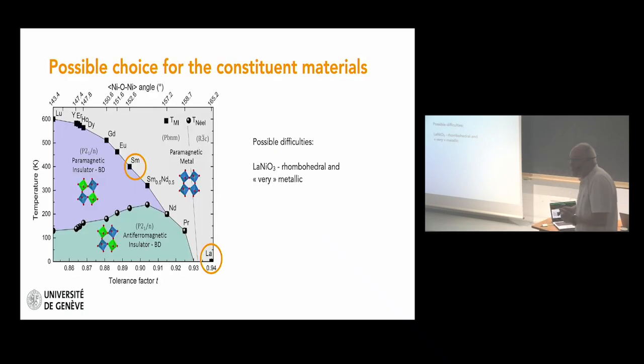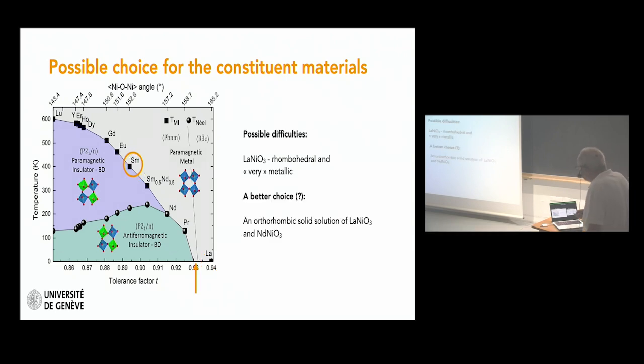We go back to our phase diagram, and a simple choice at first would be to take lanthanum nickelate, which is metallic, and maybe combine lanthanum nickelate with samarium nickelate. But lanthanum nickelate is rhombohedral, so we have another structure, and we thought maybe it will complicate things. And also lanthanum nickelate is very metallic, so maybe it's not the best choice. So what we decided to do is to move a little bit in the phase diagram and try to find a material which is orthorhombic, which is metallic, but which is a bit closer to an insulating state.